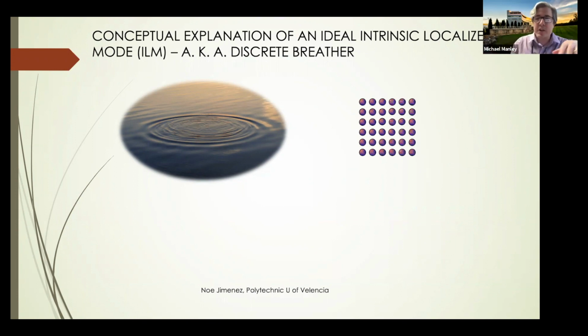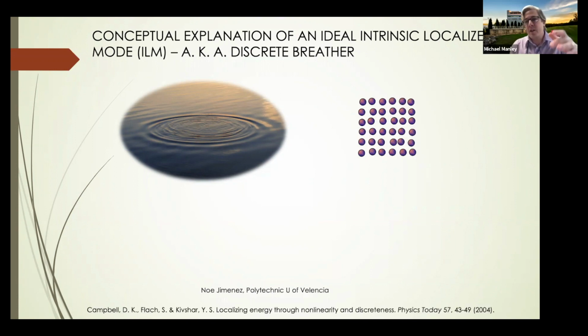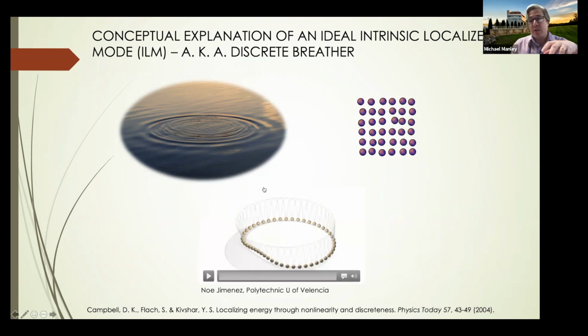And that's the same thing with a crystal. If you vibrate a single atom in a crystal, it'll resonate with everything around it, and so it'll propagate waves outward. But that is not necessarily true when you introduce nonlinearity. The reason is that with nonlinearity, the frequency of the vibration, or the elastic properties locally, can be altered by the vibration itself. So if you have a soft nonlinearity, it can create a lower frequency locally. If it's a hard nonlinearity, a higher one. So you could have some jiggling atoms that are occurring at a higher frequency than you expect. And it occurs in really simple systems.